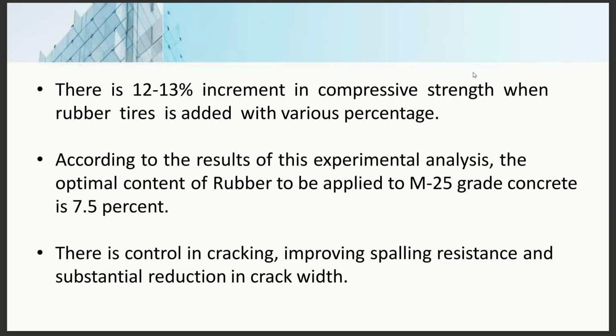There is a 12-13% increment in compressive strength when rubber tire is added in various percentages. According to the result of the experimental analysis, the optimal content of rubber to be applied to M25 grade concrete is 7.5%. There is control in cracking, improving spalling resistance and substantial reduction in crack width.